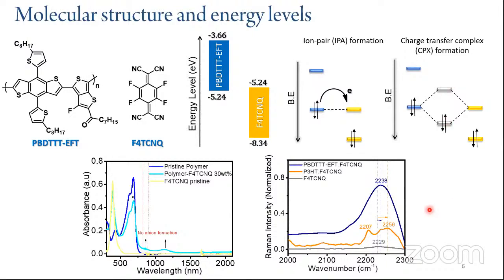And coming to our UV-visible-NIR spectra, upon doping, we can see that the strong pi to pi star transition decreases in intensity, and new absorptions in the NIR region are visible, increasing with increasing dopant concentration. This corresponds to the polaronic absorption that is caused due to the interaction between the polymer as well as the dopant. And the polaronic absorptions P1 and P2 can be seen here. And we can see there is no anion absorption corresponding to the F4TCNQ dopant at the 800 nanometer region. So we assume that the mechanism of doping is via the charge transfer complex formation, or the CPX formation.